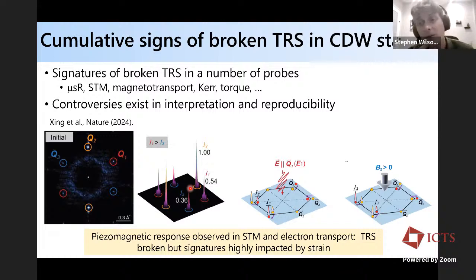The previous report, originally by Zahid Hasan's group at Princeton, was that a magnetic field could in fact couple to this charge density wave phase and switch the winding, okay? So what Vidya's group was able to do is, first of all, reproduce that magnetic field coupling, switching this charge density wave phase. And then they further showed that they could use linearly polarized light. When the polarization is along one of the endpoints, they can similarly flip the apparent chirality on the surface, with both a linearly polarized light pulse as well as an out-of-plane magnetic field. So the claim there is that they've uncovered a piezomagnetic response in the system, which would imply that time reversal symmetry is broken in the zero field state.